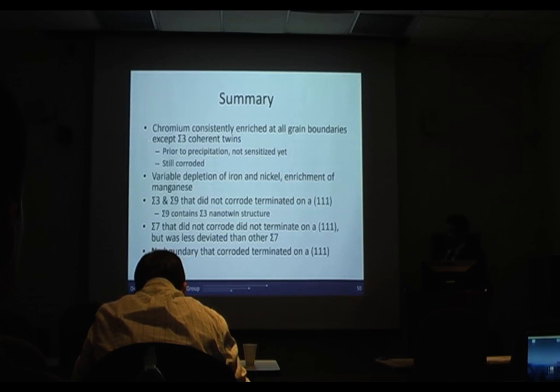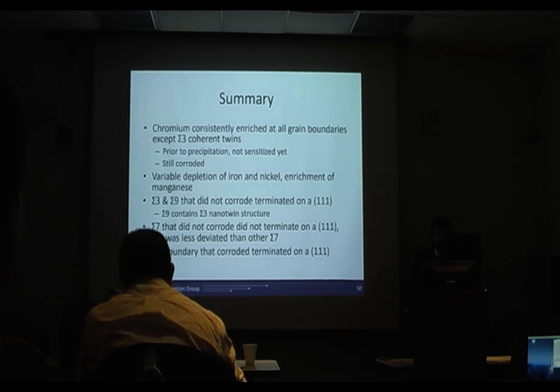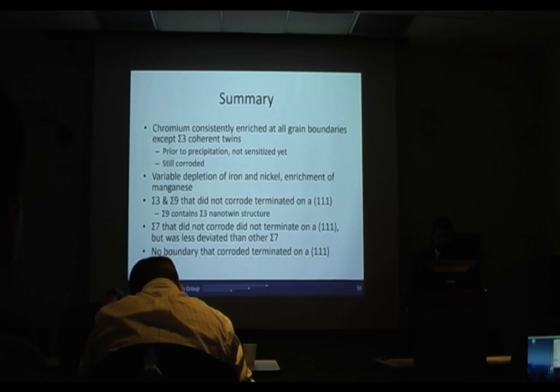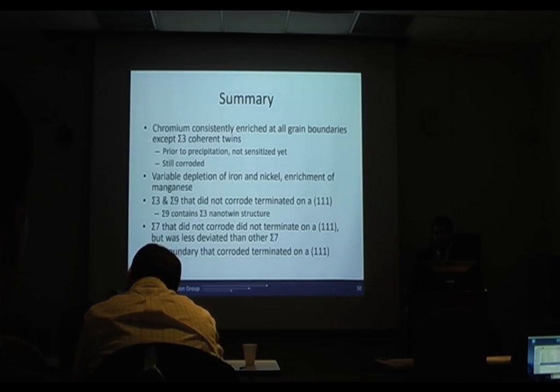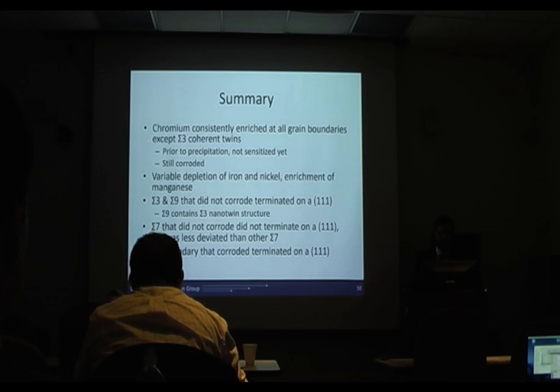So, in summary for this section, the chromium consistently enriched at all grain boundaries except the sigma 3 coherent twins. Prior to precipitation, this indicates that precipitation hasn't happened yet. We have an increase in the chromium level, so it's not classically sensitized yet because we don't have the depleted region, but it would be the early stages of sensitization. However, it's still corroded, which...